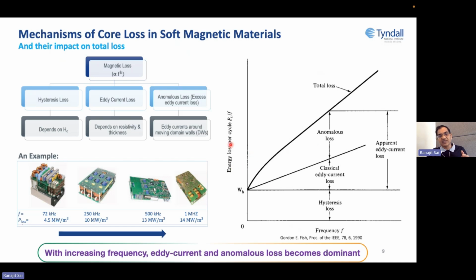Here we have plotted the energy loss per cycle, so divided by frequency, please remember it, versus frequency. So we can see that the hysteresis loss at lower frequency is the dominating loss. So we have to have a super soft magnetic material. But if you go to higher frequency, hysteresis loss is not a big concern. The biggest concern is the eddy current loss and anomalous loss. And that means we need to have a magnetic material which has much lower eddy current loss and much lower domain wall motion related loss, which is essentially kind of excess eddy current loss, you could call it. So it's a paradigm shift in some way in choosing appropriate magnetic material for this high frequency application.